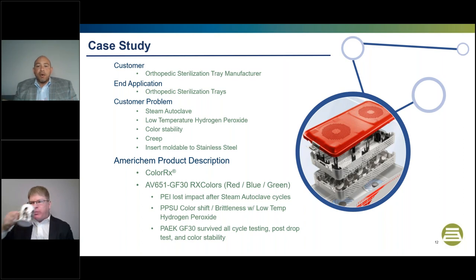But basically, you have an orthopedic sterilization tray that sees multiple sterilization cycles. We use a shotgun approach where we basically tell them, hey, these are the polymers that will work for your application. We do the color matches very quickly in all those polymers, send them color chip coupons and tensile bars, and then have them do the autoclave and the sterilization testing and see what they find. So in this case, Ultem lost impact with the steam autoclave cycle. Radel had a color shift and embrittlement problems with that low temperature hydrogen peroxide. The PEEK or PAEK Avaspire, which is in the PEEK family, survived both sterilization processes.